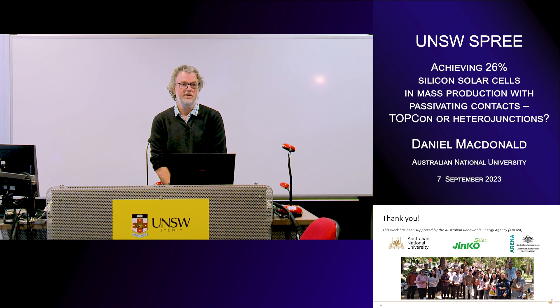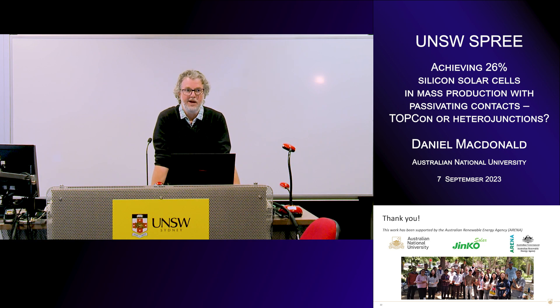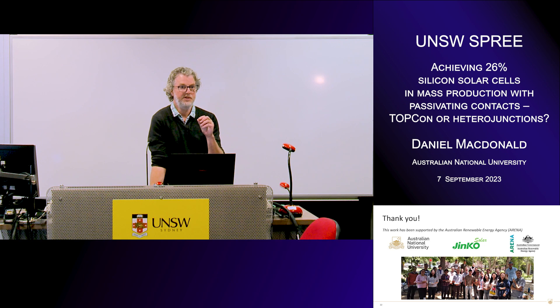The other question was about gettering. You were talking about phosphorus gettering, but in the TOPCon device you have a boron diffusion. Is there any difference between boron and phosphorus-based gettering? For polysilicon layers, they're both extremely good — both boron and phosphorus poly getter iron really well. For diffused silicon it's not the case: phosphorus-diffused silicon getters iron very well, but boron-diffused silicon doesn't unless you have a boron-rich layer on the surface. But if you leave that there, you can't passivate the surface — you need to etch it off, and when you do that the iron just goes straight back into the wafer. So in the TOPCon cell, where does the gettering happen? In the N-plus poly, in the phosphorus-doped poly. Or if you were to use P-plus poly, that would still getter very well. But in the standard TOPCon cell, the boron diffusion at the front is not doing any gettering at all.